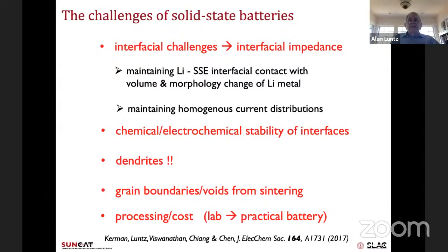So one of the issues is how do you keep two interfaces in intimate contact as the lithium is undergoing a volume and morphology change. And coupled with that is how do you maintain homogeneous current distributions at the same time so you don't get electrical hotspots. So this is a major issue. When they're not in good contact or don't have a homogeneous current distribution, you'll always get very high interfacial impedances, high resistances at these interfaces. And then you won't be able to get any current through the battery. So that's one major issue.